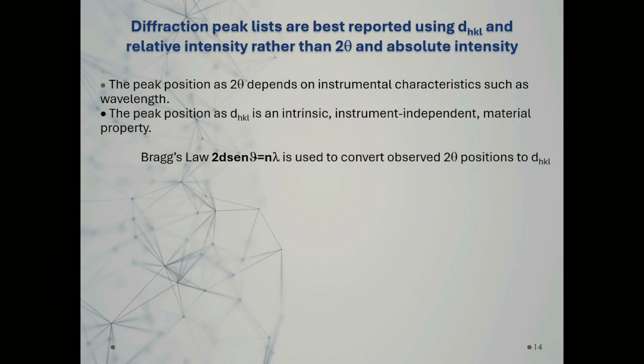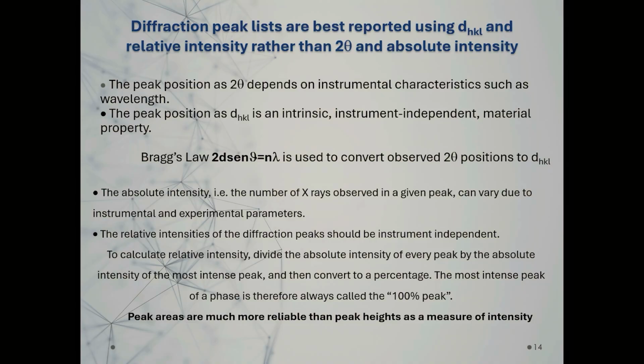So the diffraction peak lists are best reported using d-hkl and the relative rather than 2theta and absolute intensity, because the peak position in 2theta depends on the instrumental characteristics, such as the wavelength, while the peak position as d-hkl is intrinsic, instrument independent. The absolute intensity, the number of X-rays observed in a given peak, can vary due to the instrumental and experimental parameters that we use. Instead, relative intensity should be independent. To calculate relative intensity, divide the absolute intensity of every peak by the absolute intensity of the most intense peak. Peak areas are much more reliable than peak heights when measuring intensity.